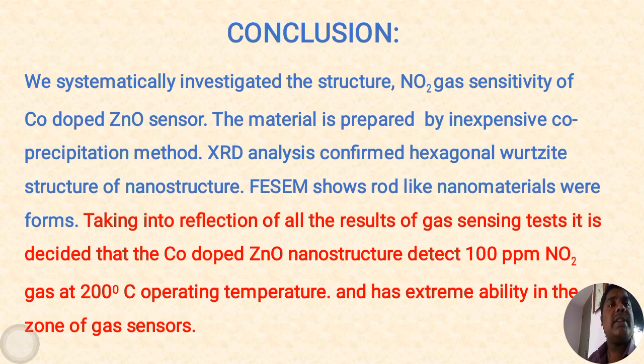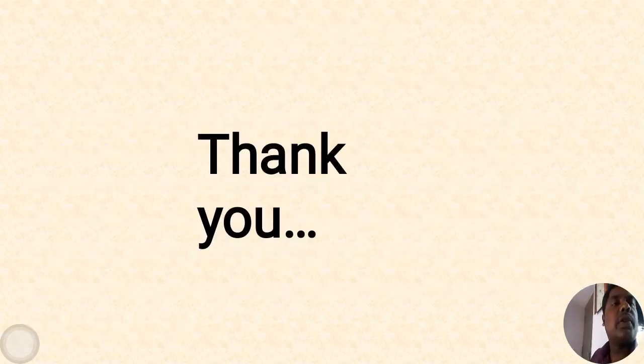And last one, that is the conclusion. We systematically investigated the structure and NO2 gas sensitivity of cobalt doped zinc oxide with the help of a simple and inexpensive co-precipitation technique. XRD analysis confirmed hexagonal wurtzite structure of the nanostructure. FESEM showed rod-like nanomaterial was formed. Taking into consideration all the results of gas sensing tests, it is decided that cobalt doped zinc oxide nanostructure detects 100 ppm NO2 gas at 200 degrees Celsius operating temperature and has extreme ability in the field of gas sensors, and therefore cobalt doped zinc oxide is a very important material for NO2 gas sensors.